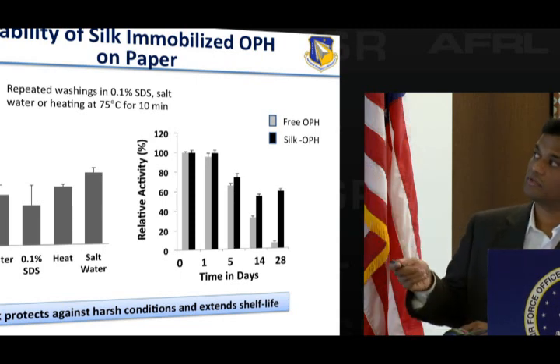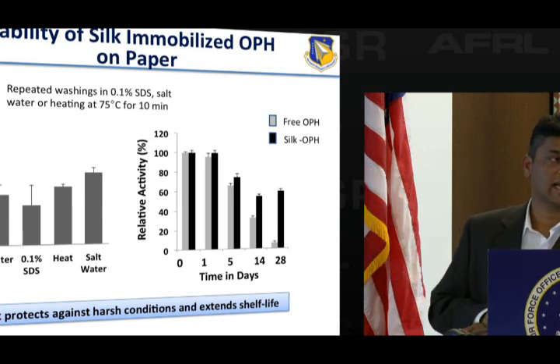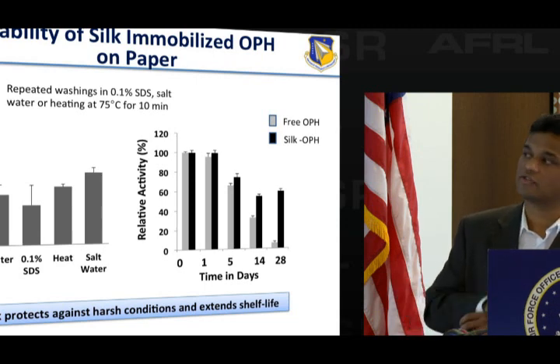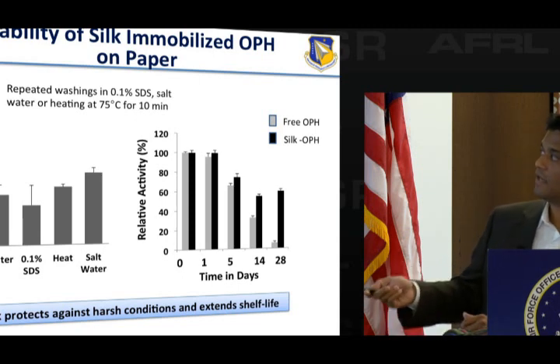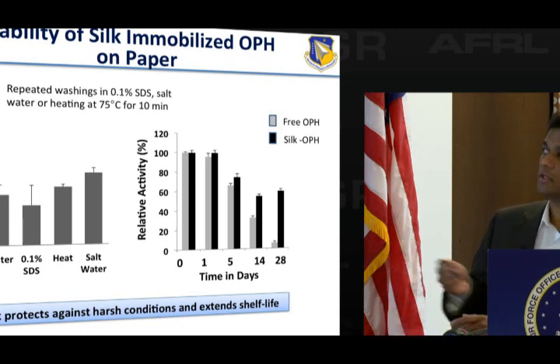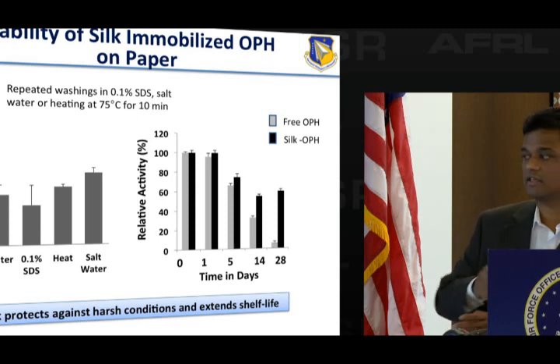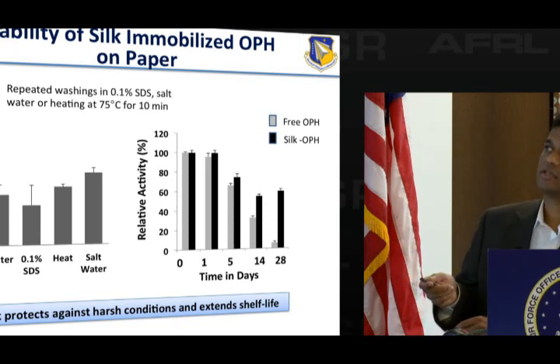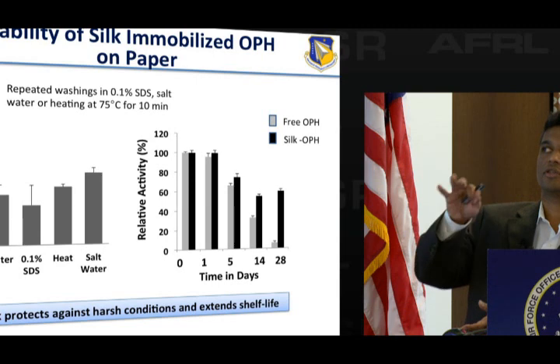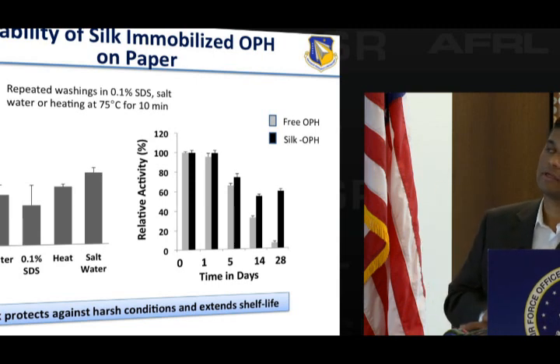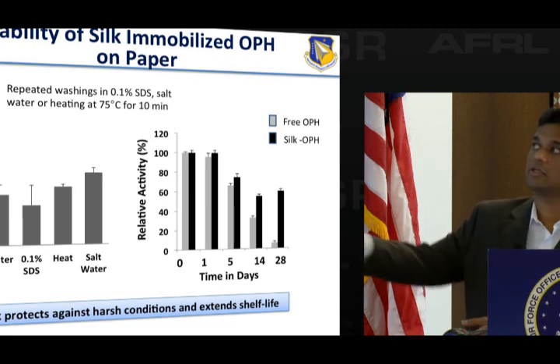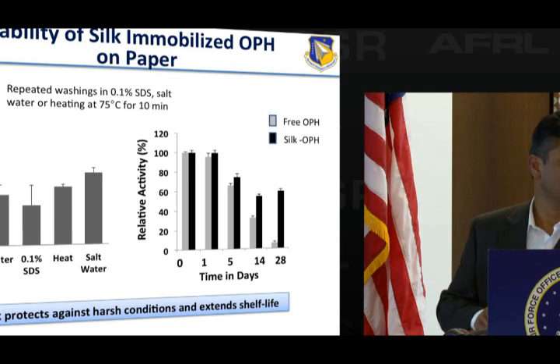We washed it so many times in that solution, and you can still retain the activity. You can put it in heat, SDS. It doesn't seem to kill it. The activity is reduced, but you can still get a positive signal from it. And you can have that at room temperature for about 28 days, and it still works. Okay, so this is a very nice, I think, in my mind, a transition of a 6-1 program on trying to understand structure-property relationships of silk, encapsulating enzymes, and actually developing a simple device, a paper-based device for that.